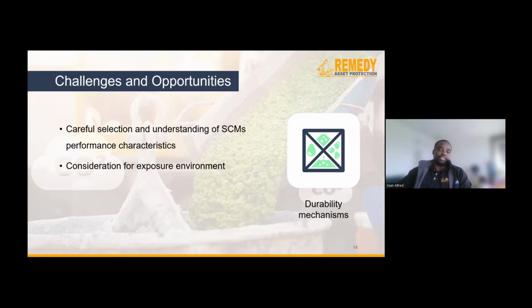And the challenge that we have is that some of these SCMs have low pH, which translates to higher carbonation rates compared to OPC. But then the pore refinement reduces transport rates. Now, in this case, considerations can be made of using surface treatments, which may be a value add to the durability performance of these materials if we do decide to use them. And so we can therefore say that different durability indicator methods are required to gain a better understanding of the durability characteristics that you would get from using different mixed proportions of the SCMs that are included in the concrete mix designs, tied to a specific environmental or exposure condition.